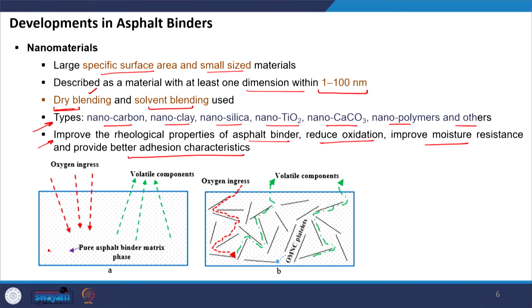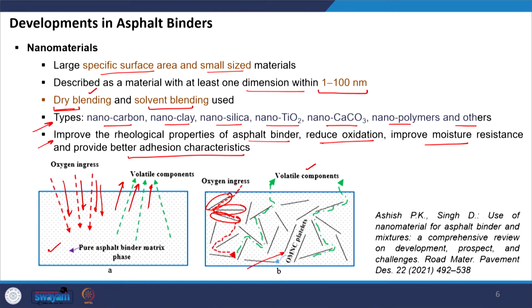So you see, when you have a normal binder and oxygen ingresses in this way, it has a direct path to come in and attack the bitumen. Similarly, the volatiles or the lighter components in the bitumen are free to move whenever the temperature increases. But when you have nanomaterials, they interfere with these processes. For example, you can see the path of the oxygen ingress is hindered by the presence of the nanomaterials within the bitumen system. Similarly, you can see how the volatile components find it difficult to go out once the temperature is increased because of the presence of these nano platelets. So this is the review paper which you can refer to for more details about the use of nanomaterials in asphalt mixtures.